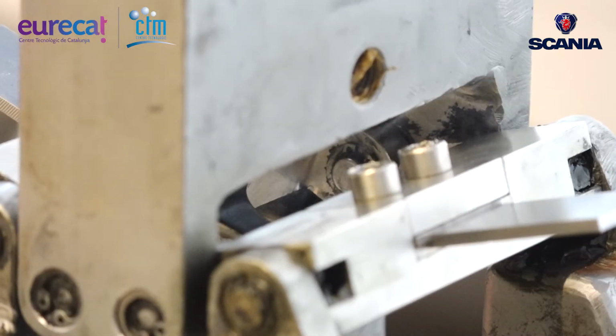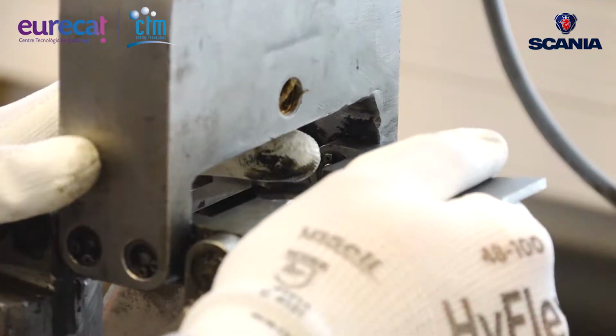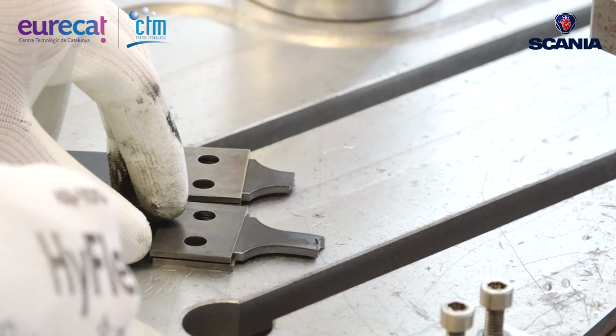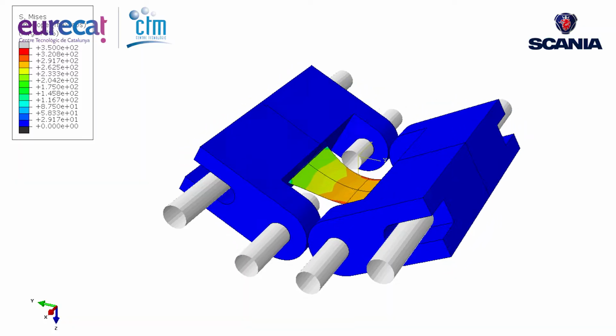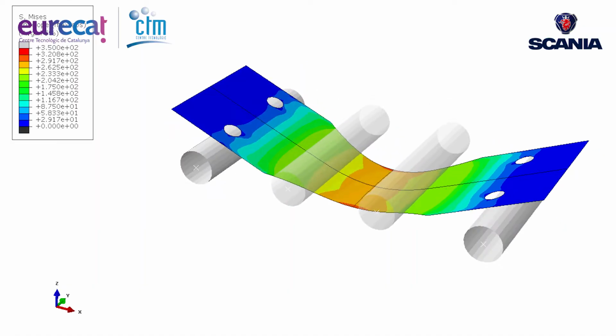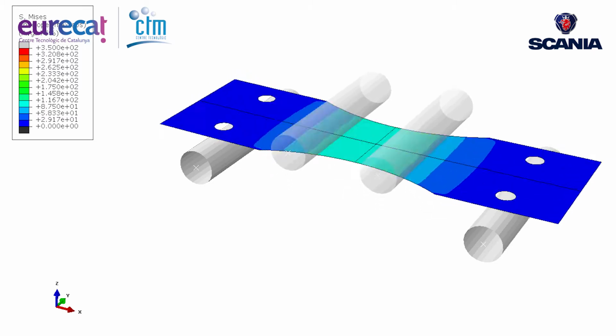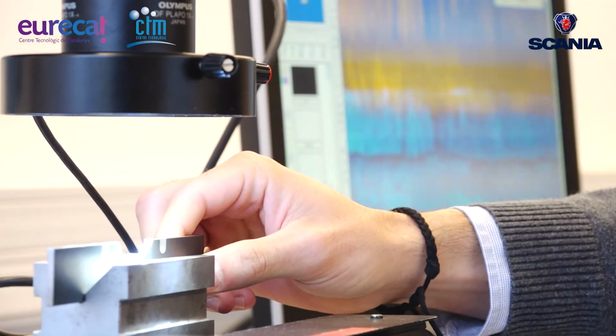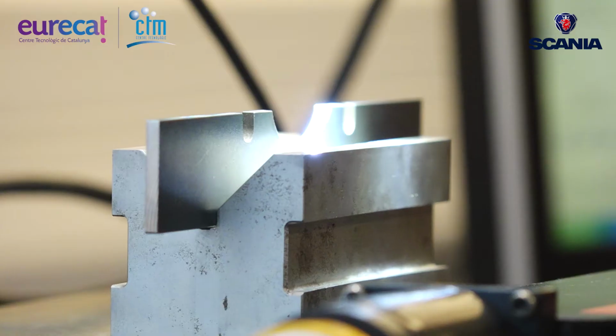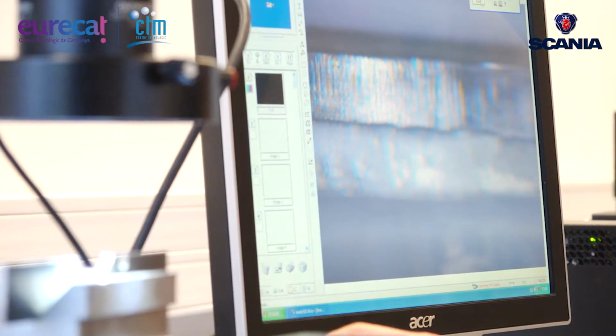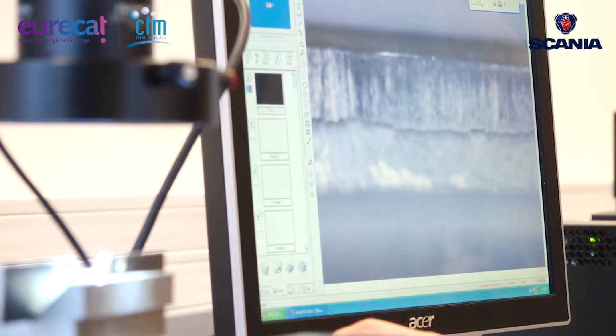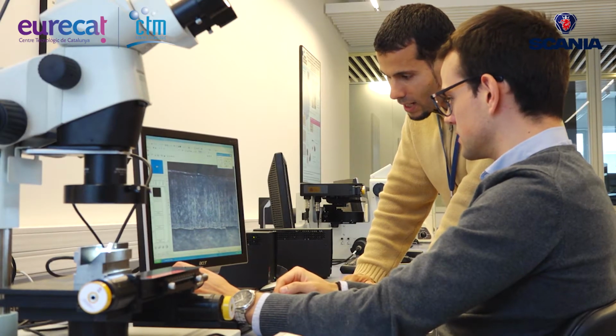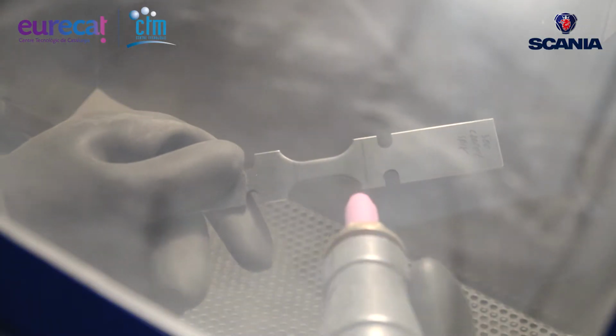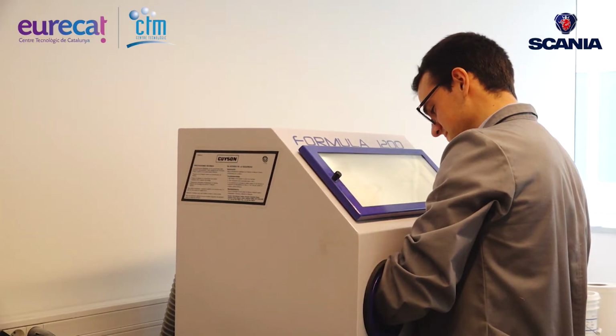Fatigue is a phenomenon that defines how cracks are formed and grow through the material under cyclic loads. It is highly influenced by surface effects, in this case located on the trim edge. The trim edge is characterized by a typical shape that can be improved with a correct trimming clearance and secondary operations such as blasting operation. The blasting operation introduces residual compressive stresses, reduces the surface effects and also the roughness value.